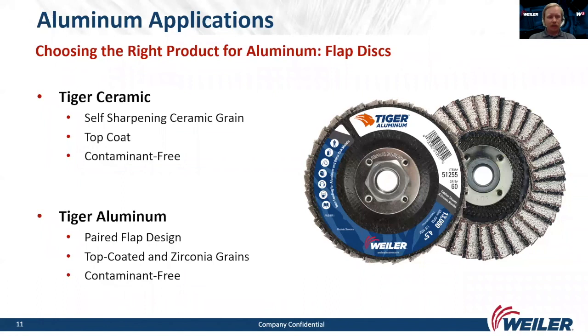So let's talk a little bit about the Tiger Ceramic flap disc, and then we'll talk about the brand new Tiger Aluminum flap disc, as you can see on the screen here. Again, Tiger Ceramic, self-sharpening ceramic grain, has that top coat to keep everything cool as we're grinding. And we're minimizing loading with all of these top-coated products. And again, contaminant-free. We have the versatility again of the ceramic grain, being able to do carbon, stainless, and aluminum, while the Tiger Aluminum, specifically formulated for aluminum processing, is going to give you the best performance on aluminum. This was tested on 3000, 5000, and 6000 series aluminum, and we know it works very well on all of them.